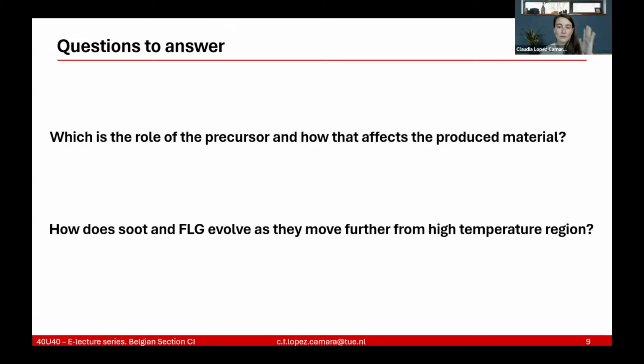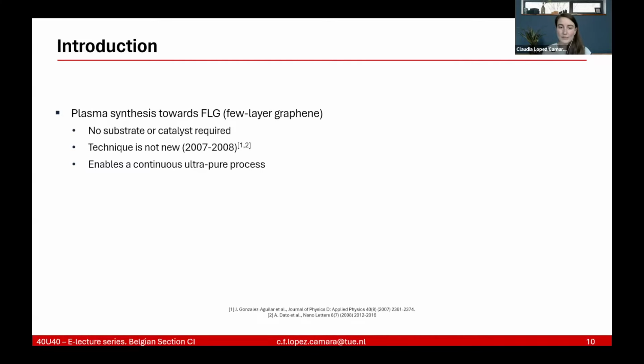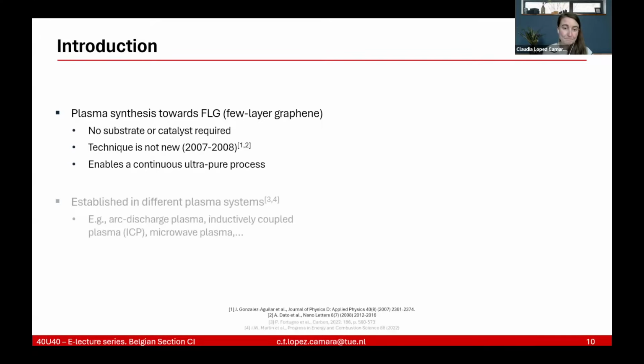Because in between the time of creation of the material and the time that we can collect it in the filter, there was not really anything known in terms of actually sampling it, rather than doing, for example, laser diagnostics. Therefore, we thought, what is the best gas phase approach to do it? And we thought that perhaps plasma would be the best, because plasma synthesis for creating few layer graphene is a technique that does not require substrate or catalyst. It's not new, and it also enables an ultra pure process, which makes the questions easier to answer, rather than having external things that might change the answers or change the process. Then it's also established for different plasmas to create graphene. Therefore, we thought, why not? Let's do a microwave plasma synthesis.